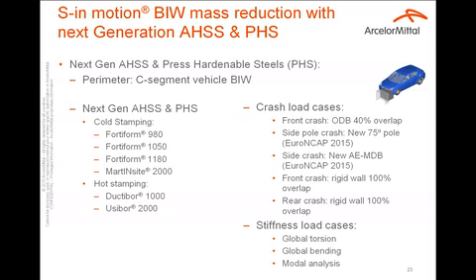We used our new Fortiform family for cold stamping, Fortiform 980, Fortiform 1050, Fortiform 1180, and also the last martensitic grade in development, 2000, and also our two new grades for hot stamping, the Ductibor 1000 and Usibor 2000. We took into account, as explained before, all the major crash load cases to assess the solutions in front, side, and rear impact, and also stiffness load cases were taken into account, like global torsion, bending, and modal analysis.